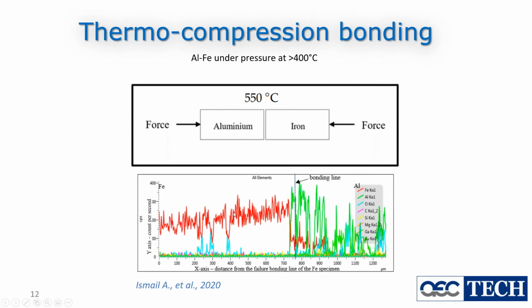So that's why aluminum can diffuse into iron and then make a new phase or dissolve in the iron, so the boundary will disappear very fast. There's another bonding called thermo-compression bonding. If aluminum is under pressure with iron at higher than 400 degrees C, which is always the case in extrusion, it makes thermo-compression bonding. How it happens is you have atoms of aluminum diffusing into the iron and atoms of iron diffusing into aluminum because they're dissolving each other. And then your boundary disappears.